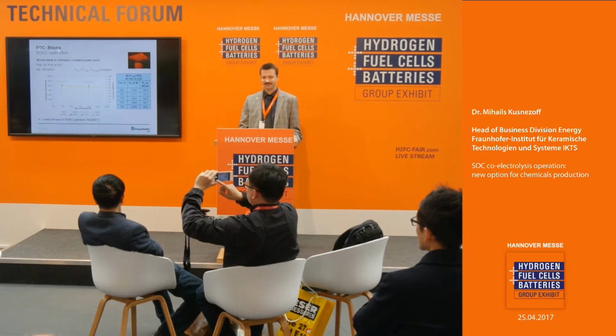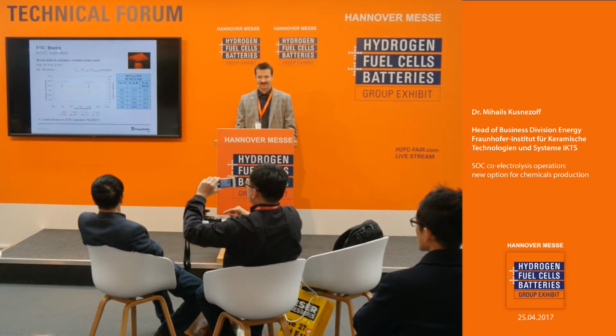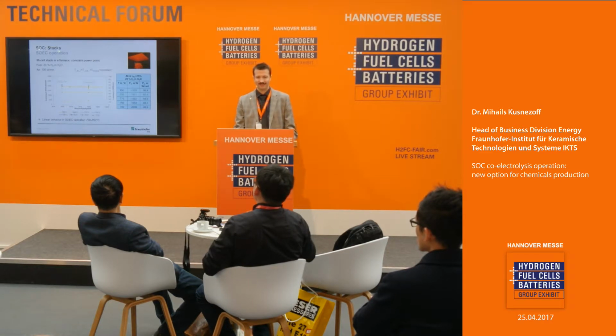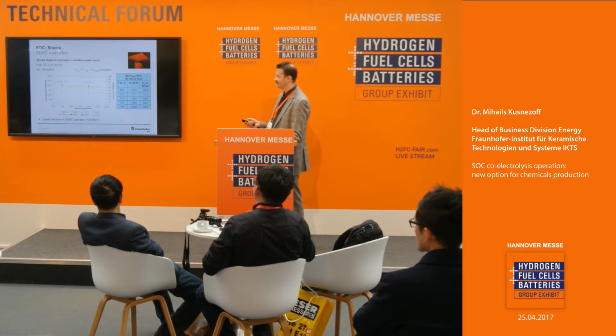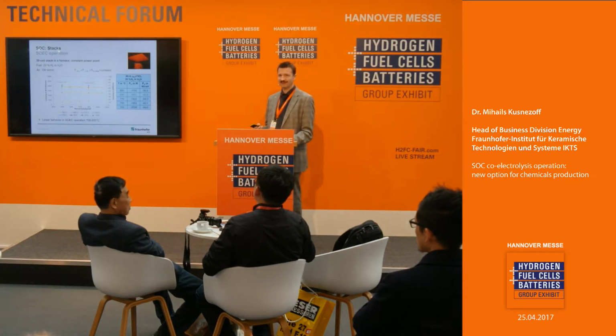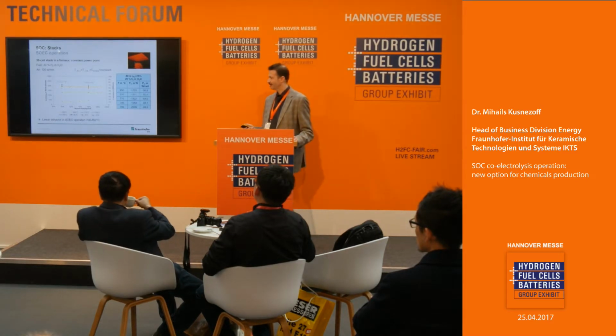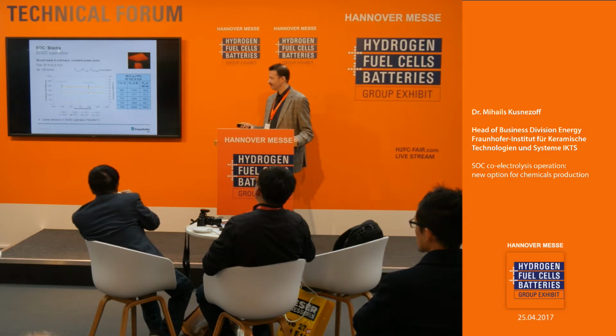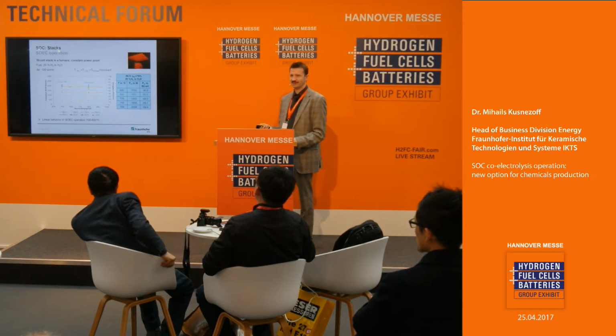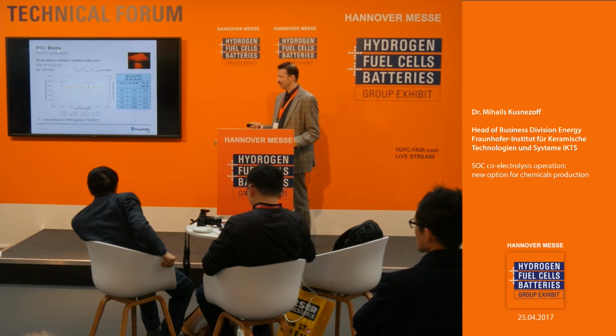In electrolysis operation, we apply power. So we can also generate a performance map, but in this case we need some heat source to operate the stack, and this is the furnace which we have used. And then we have simply looked at the thermoneutral operating point. It means we have achieved the same temperature of inlet air as of outlet air, adjusting the current. And here you see the power we need for thermal neutral operation of such a cell at different temperatures. And you see also, increasing the temperature, we reduce the power consumption.